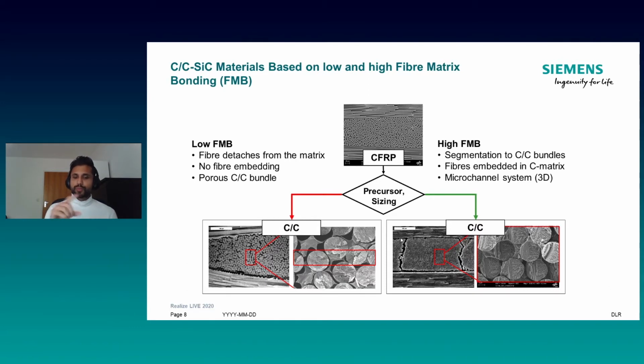I will end up with a microstructure which has pores distributed all over the matrix. As you see on the left-hand side of the screen, you have pores where the fiber detaches itself because of the low fiber matrix bonding, and we have pores inside the matrix. On the other side, if we have high fiber matrix bonding, and the fibers are kept intact to the matrix because of the forces, then we end up with a block of carbon-carbon, right? So we have a carbon-carbon block where there are no pores within this block, but the pore channels, which we need for the further step, the siliconization step, as I showed in the previous slide.